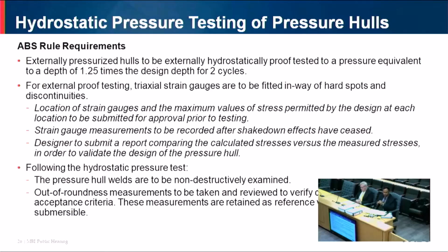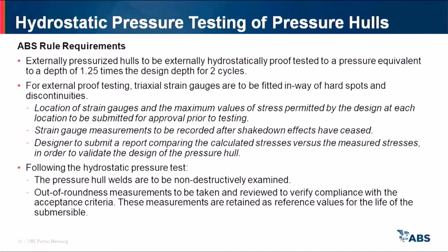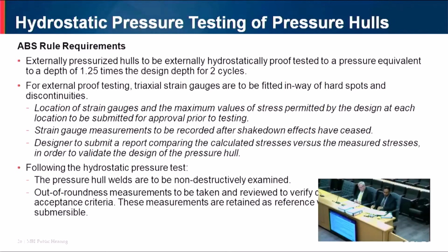So what happens if you pressure test the hull and start recording the strain gauge measurements before shakedown has ceased? You will note that the strain gauge measurements on the first and second cycles do not match. That is because shakedown is still taking place. So after shakedown has ceased, you will see the readings on the strain gauge on the first and second cycle will match, okay? So typically to verify that shakedown has ceased, you will pressure cycle the hull for a number of cycles, and then you will check the strain gauge readings. Once you confirm that the readings match, that is the point when shakedown has ceased, okay? And those are the readings you actually use for your hydrostatic pressure testing.